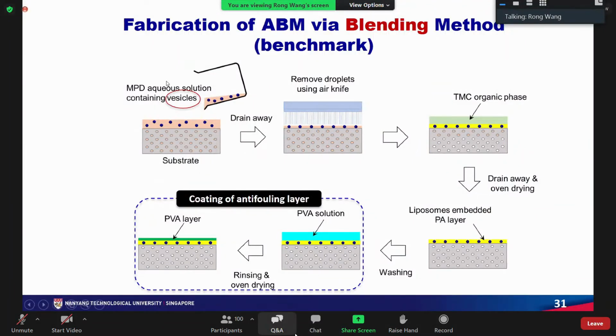The second step is to incorporate aquaporin into the selective layer. First, we use the blending method. That's the conventional method that we used before. This means we mix the aquaporin-containing vesicle with the MPD aqueous solution, then go through the normal interfacial polymerization procedure. And finally, we use the PVA coating to form the antifouling layer.